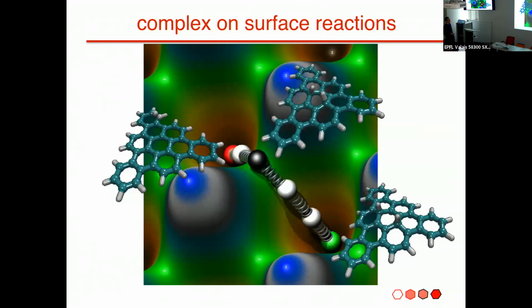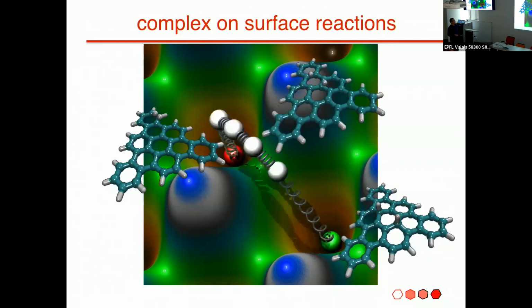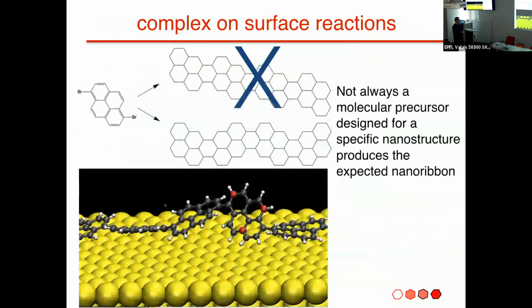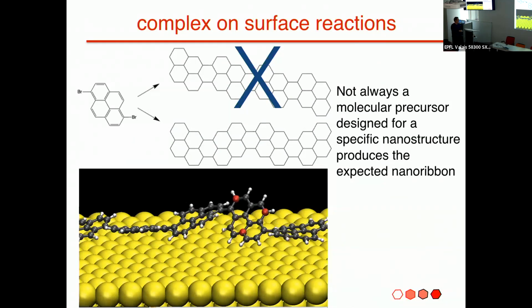Unfortunately, if we deal with fully ab initio simulation for this kind of system, it's difficult to go beyond methods like NEB to characterize a transition state. And what is difficult in a NEB calculation is to create a clever guess for this initial path. Typically, a guess for the NEB path is a linear interpolation between the initial state and the final state, but you can easily imagine that if I am dealing with the rotation of a segment, I cannot do a linear interpolation, because otherwise I would have intermediate configurations where the atomic configuration does not make sense.